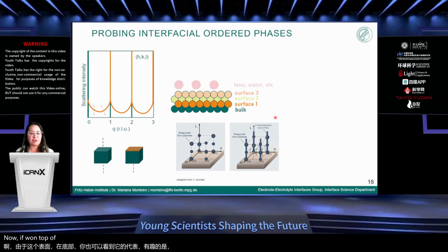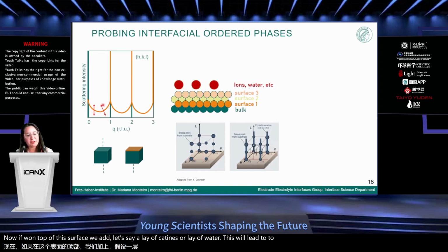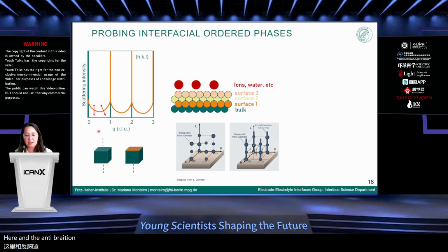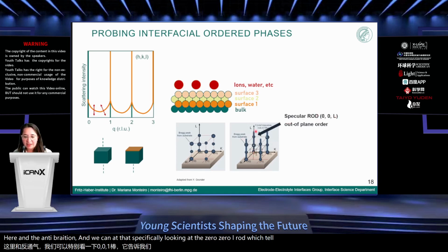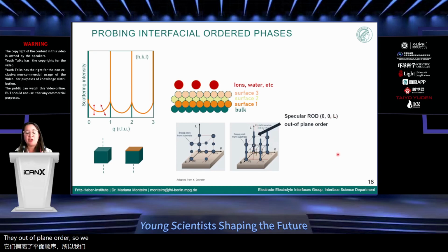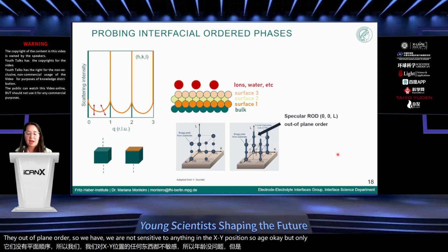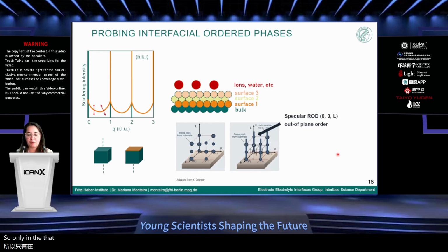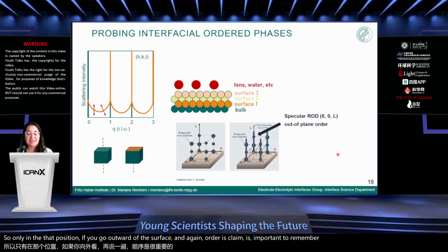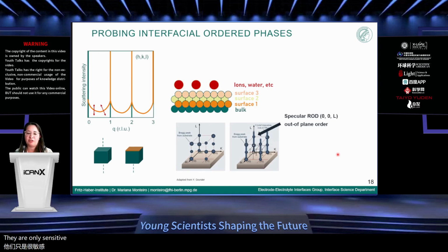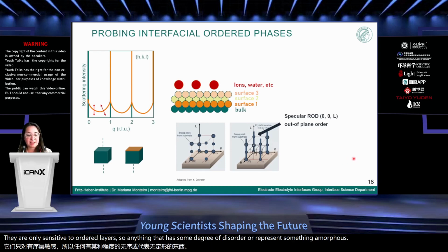Now, if on top of the surface we add, let's say, a layer of cations or a layer of water, this will lead to very specific changes in these anti-Bragg positions. And we can look at that specifically by looking at the 00L rod, which tells us the out-of-plane order. So we are not sensitive to anything in the XY position, so H and K, but only out of plane, so only in the Z position if you go outward from the surface. And again, another disclaimer: it's important to remember that this is a diffraction technique, so we are only sensitive to ordered layers. Anything that has some degree of disorder or is amorphous, we will not see a signal from.